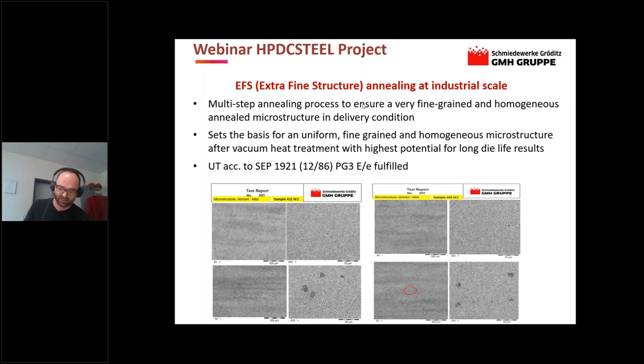The forged and annealed block was ultrasonic tested and fulfilled the requirements EE according to SEP 1921. On the bottom of this slide, we can see microstructure pictures in different magnifications, 50:1 as well as 500:1. It can clearly be seen that on the block bottom as well as on the block top, in the core position, the obtained annealed microstructure at 500:1 clearly fulfills the typical requirements of national and international annealing structure standards.